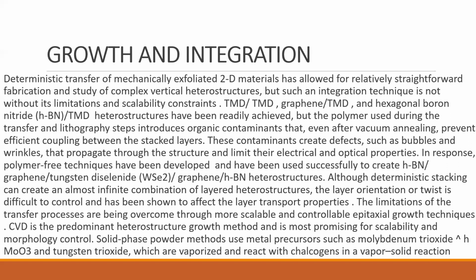These contaminants create defects such as bubbles and wrinkles that propagate through the structure and limit their electrical and optical properties. In response, polymer-free techniques have been developed and have been successfully used to create hBN, graphene, or tungsten diselenide, graphene, or hBN heterostructures. Although deterministic stacking can create an almost infinite combination of layered heterostructures, the layer orientation or twist is difficult to control and has been shown to affect the layer transport properties.